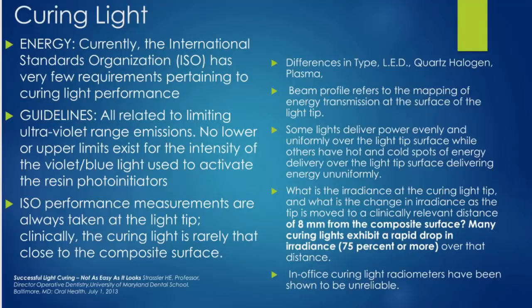So the important thing to get from this slide is that when we look at the energy and the guidelines set forth about curing lights, we talk about ISO performance. That's how they're measured. And when we talk about what ISO performance really tells us, it's telling us what's happening directly from the light tip to the restorative material, and it is not assuming that the light could be further than 1 millimeter away from the tooth structure. So always keep that in mind when we talk about ISO performance.